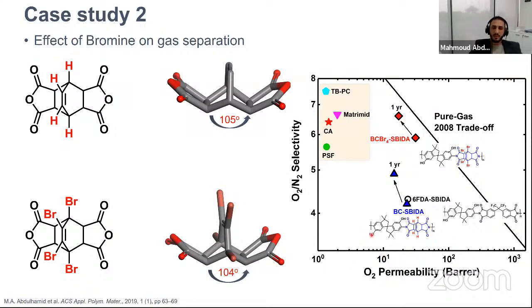So we prepared the porous polymers from hydrogen-containing polymers and bromine-containing polymers, and evaluated their performance. As you can see, if we take this point, this is a fresh material, and this is a 1-year aged material. Same for here. This is fresh, and this is 1 year. If we look at the fresh material, we can see that just by adding a bromine, we are increasing permeability from roughly 20 up to 50. So we already increased the permeability of oxygen, and at the same time increased selectivity from 4.2 up to 6. And this is a very good combination in terms of oxygen permeability and O2/N2 separation.